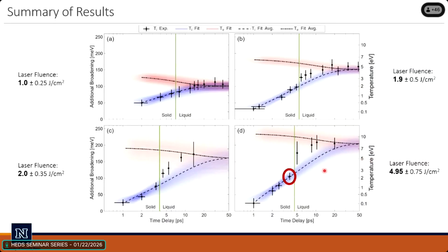But this is still a solid. There are diffraction lines still. So this is a 20,000 Kelvin solid. And we looked at that and thought, that seems pretty hot for a piece of gold. The melt temperature of gold is 1,300 Kelvin. So we're many, many, many times the melt temperature. And we thought, could we write a paper on that?